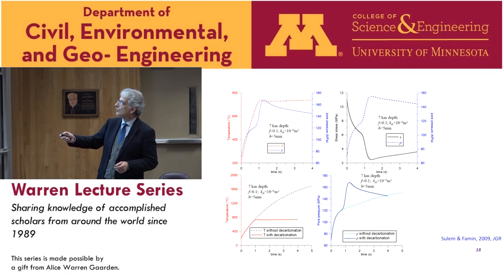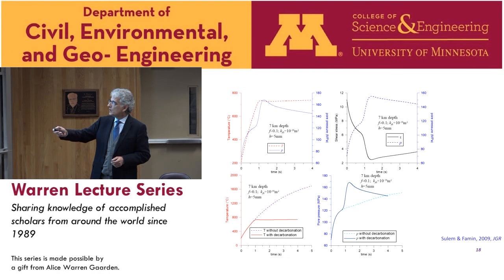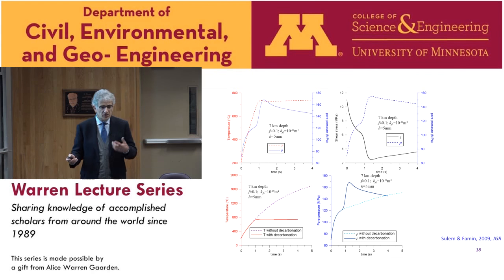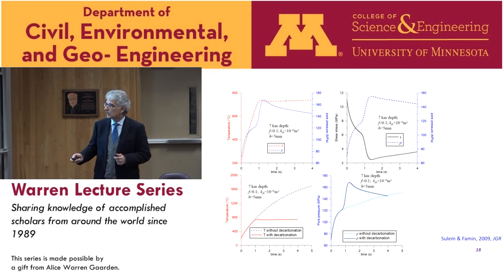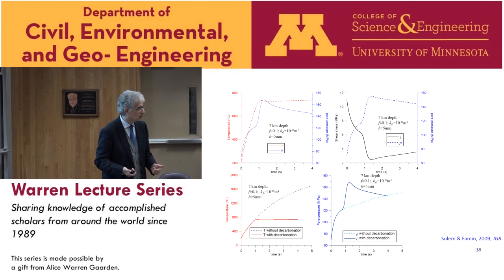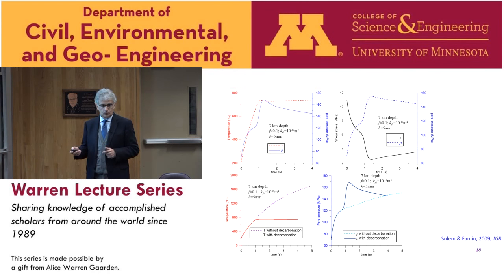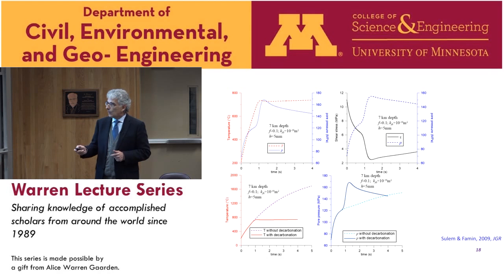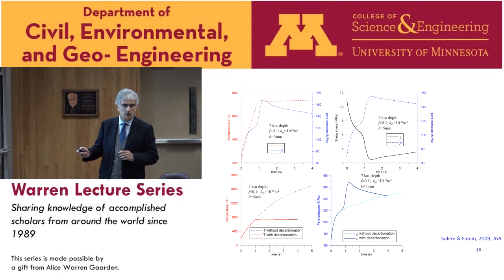And we can translate this in terms of shear resistance, with the initial weakening, stronger weakening when chemical reactions occur, and then a re-strengthening. And just to emphasize the effect of chemical decomposition, if we perform the same computations without it, and this is the curve here in a dotted line, without considering decarbonation, we see that the temperature rise can be much higher, reaching values for which melting of the rock would be possible. In all this analysis, we see that a very important parameter is actually the thickness of the shear zone.